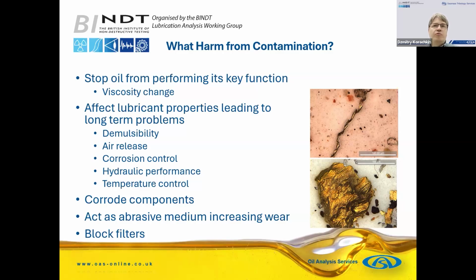It can stop the oil from performing its key function. Adam spoke about viscosity, how important it is. Many contaminants are actually affecting the bulk of the fluid. You can have fuel ingress, water ingress, ingress of a different lubricant with a different viscosity grade, and that can lead to a change in viscosity, and it can stop the lubricant from performing its key function.